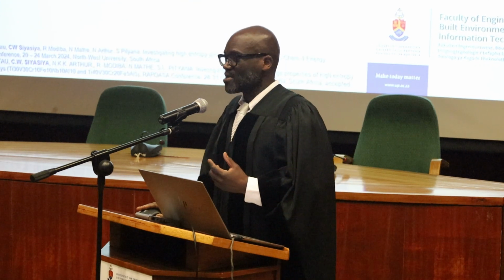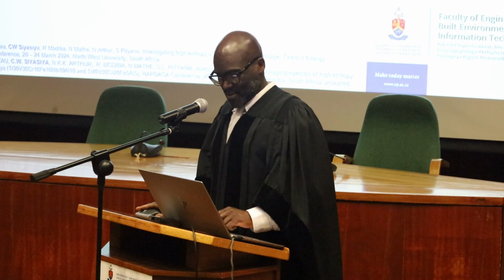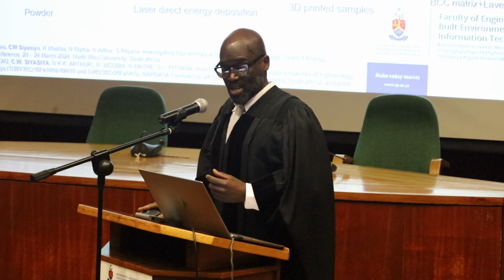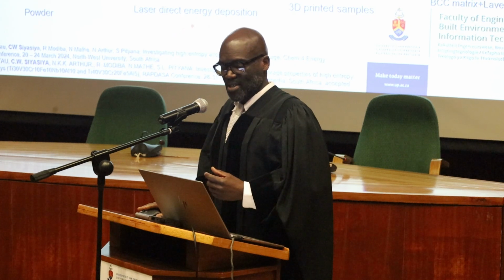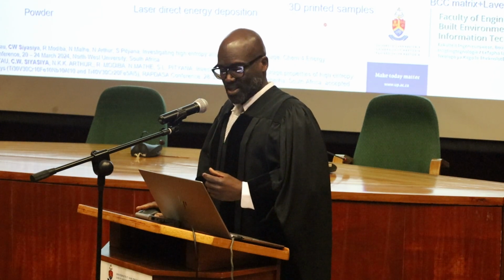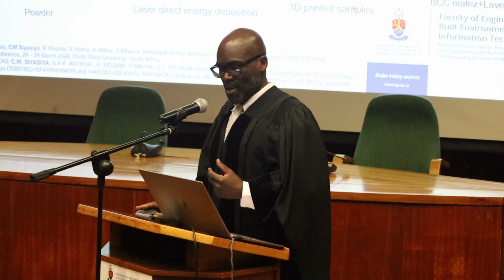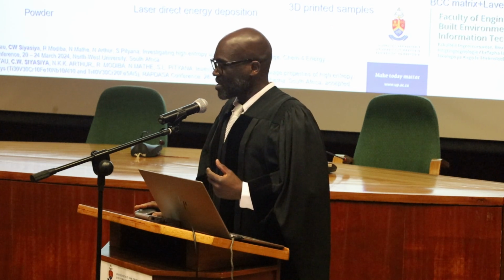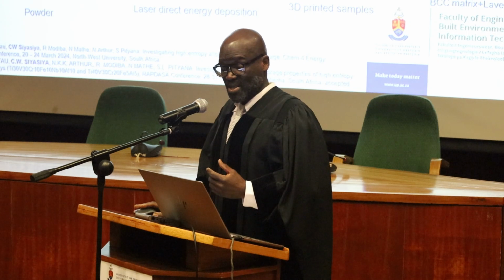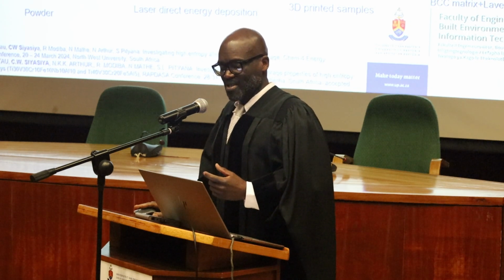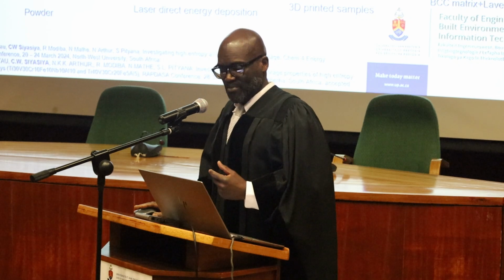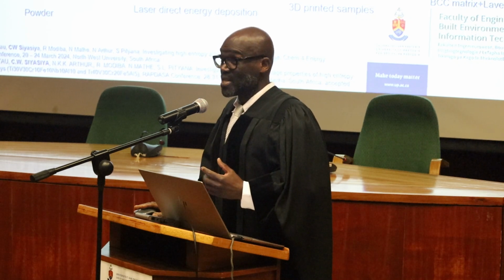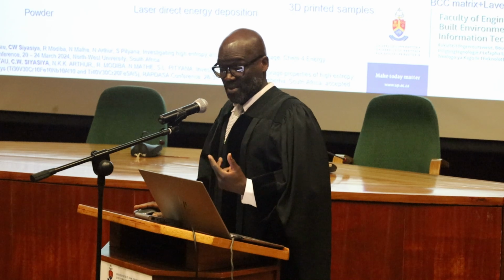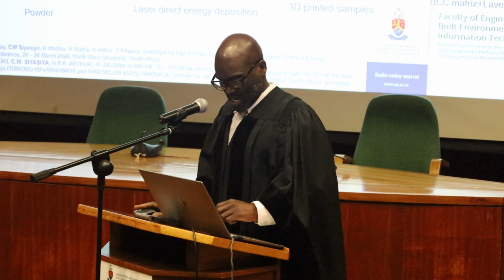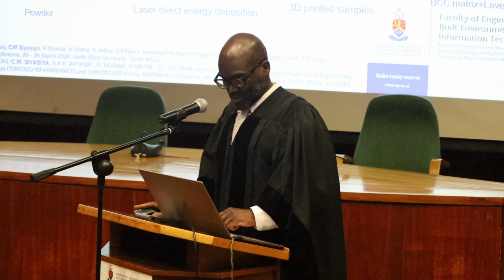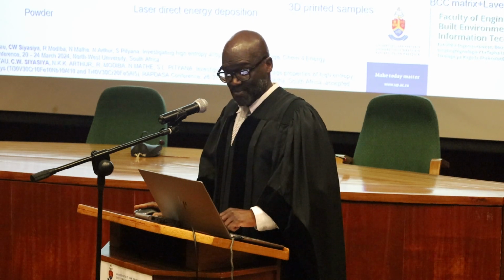In this work, after materials modeling, these two alloys were designed, and we procured some powders, and using laser direct energy deposition, the samples were printed. After printing, materials characterization was done, and using XRD, it was proven that indeed these are BCC materials, but they also contain Laves phase. The Laves phase is also good for hydrogen storage. Literature shows that, so we are yet to prove that.